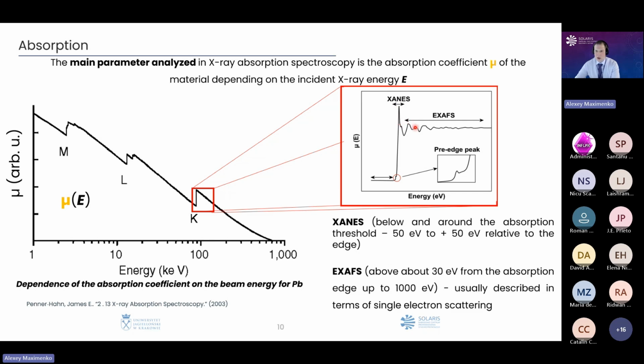And when we look at, for example, this spectrum, we could see that we could divide it into two areas. One area is called X-ray Absorption Near Edge Structure, and the other one is Extended X-ray Absorption Fine Structure. And the XANES range of the spectrum starts from minus 50 electron volts before the absorption edge to plus 50 electron volts above the absorption edge, and the EXAFS range starts above 30 to 50 electron volts up to 1000 electron volts in our spectrum.